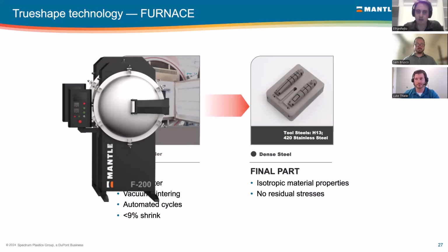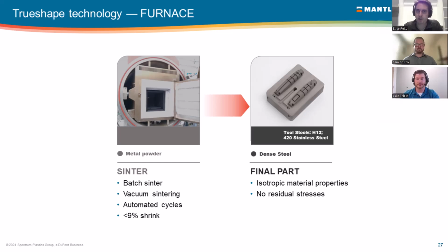Awesome. The print is complete. After the part is printed, we go into a sintering step. Here it's being placed into a furnace. The furnace gets just below the melting temperature of the material. Our furnace gets up to 1400 degrees Celsius. Any binder that was left in the paste is removed, and the part sinters, where the metal powder is fusing together, and the part shrinks about 9% in this process. What comes out is a dense, strong steel component. You can see the final part has very isotropic material properties. There are no residual stresses from that sintering process, and what comes out is tool steel.